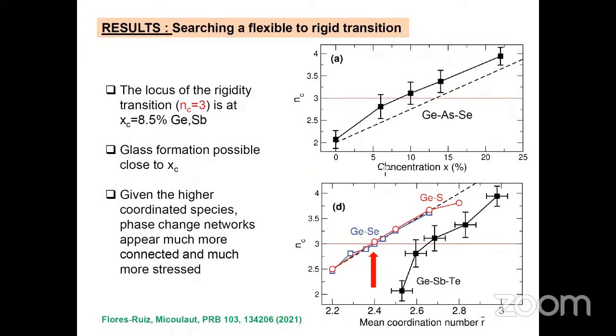So now if we focus on the number of constraints as a function of concentration in this GST with changing Ge and Sb content, we find a locus of the rigidity transition that is, Nc equals 3, at a composition which is about 8.5% GeSb. And that composition is smaller than the one you obtain for the corresponding isochemical selenide, which is found at about 13%.